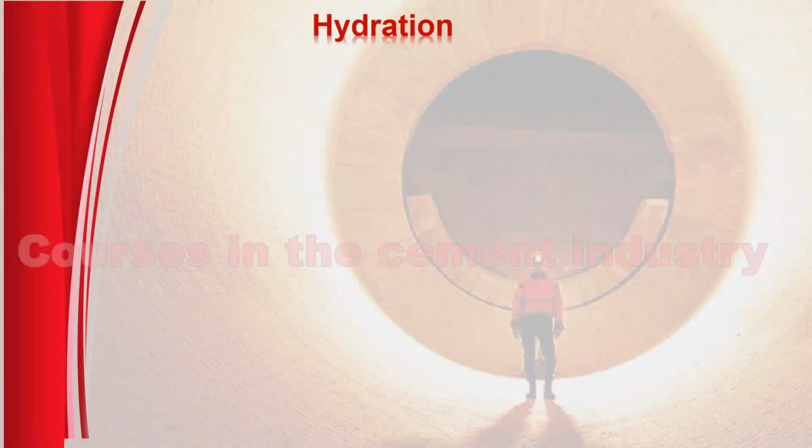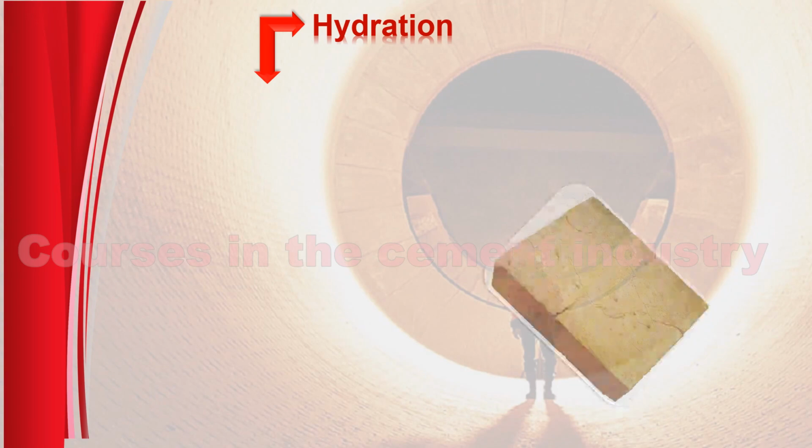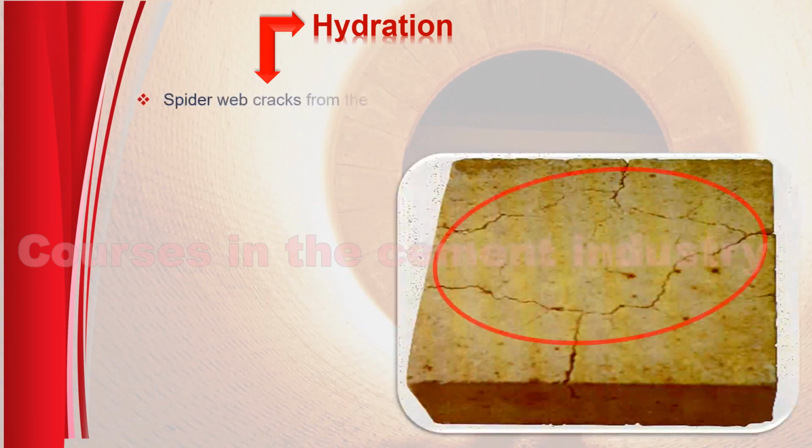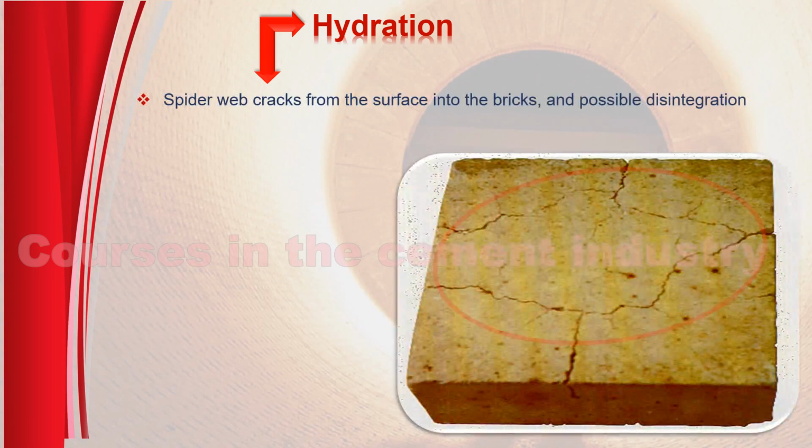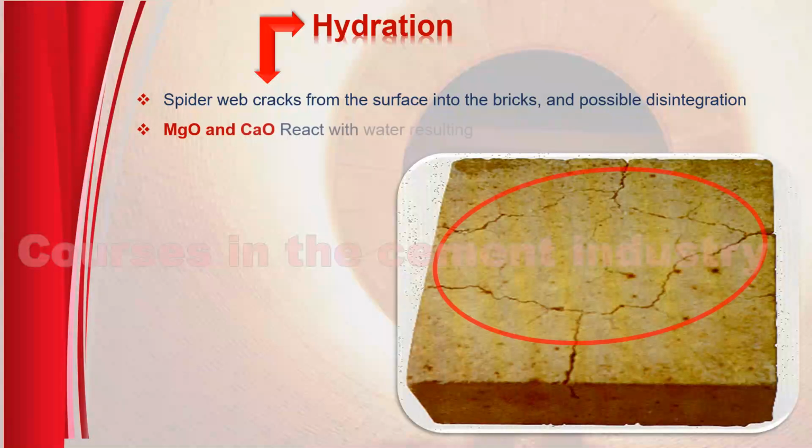Hydration. The main reasons for this are: 1. Spider web cracks from the surface into the bricks, and possible disintegration. 2. MgO and CaO react with water, resulting in a large volume increase.